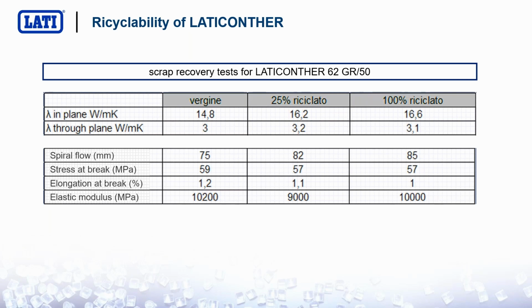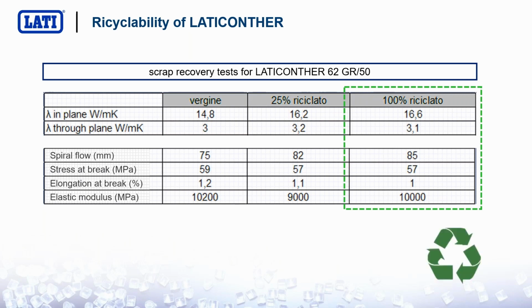This means that you can actually recycle thermally conductive plastics into virgin thermally conductive plastics with no diminishing, with no decaying of the thermal performance of your part. This means that these plastics are the best candidate to recycling. That's the reason why we are moving also forward in this evaluation, and we have also made some calculation about this. Now, let's sum up. Let's face the difference between aluminum and graphite.